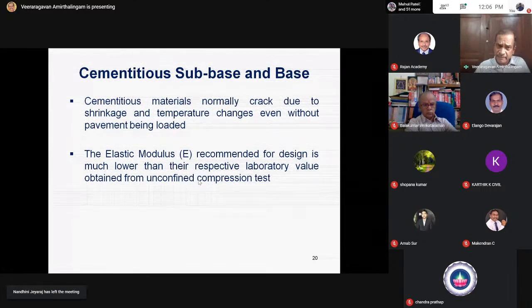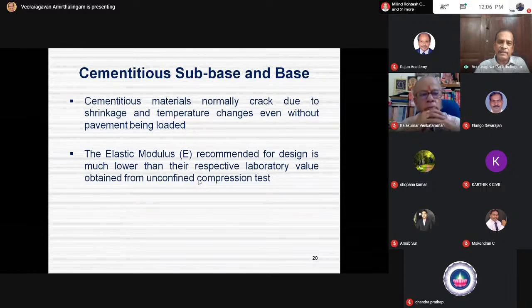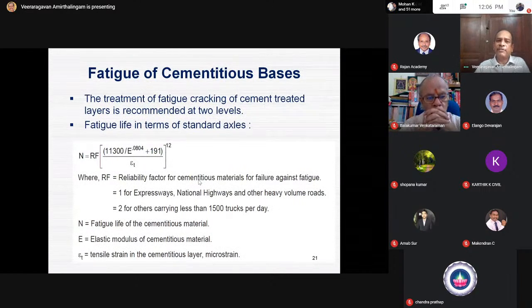Again, in addition to the radial tensile strain at the bottom of the bituminous layer, you should also consider the radial tensile strain at the bottom of the cementitious base also. So the IRC has again given a fatigue equation. It considers the elastic modulus of cementitious material. It also considers the reliability factor, 1 for expressways, 2 for other highways, and epsilon T is the tensile strain in the cementitious layer in microstrains, which means you should also know to test a beam of a cementitious base in the laboratory, find out at what strain value it fails.